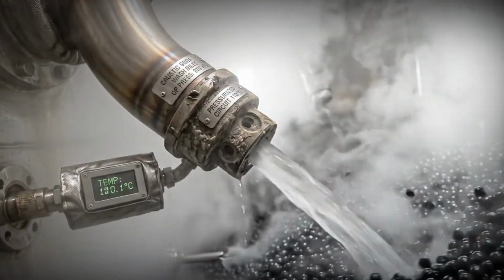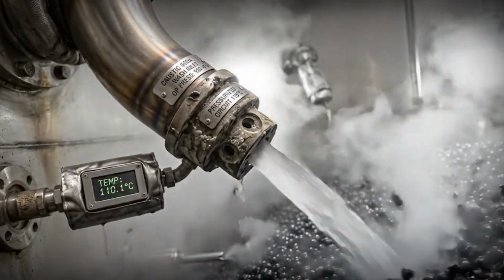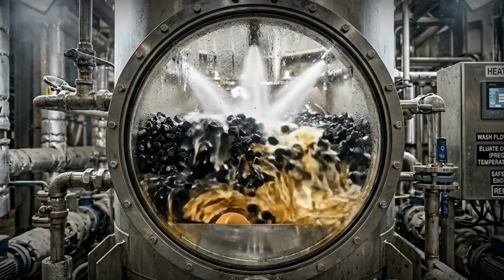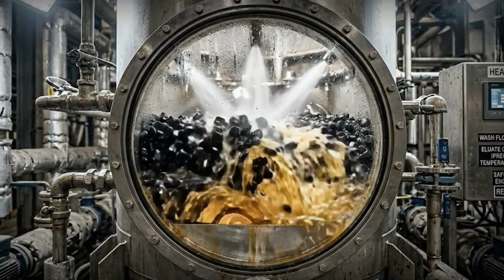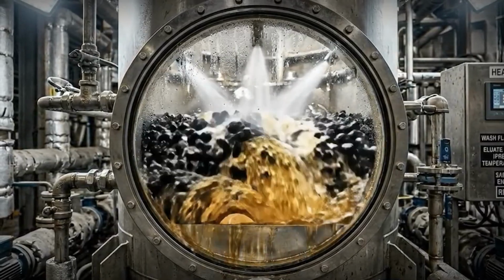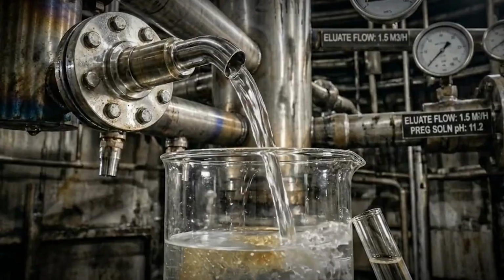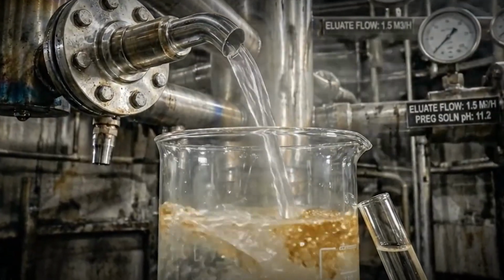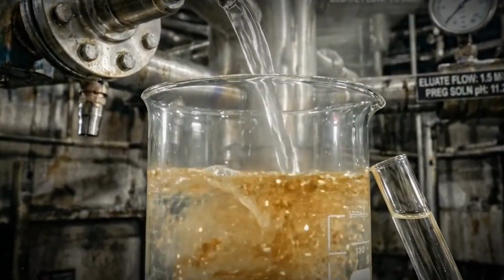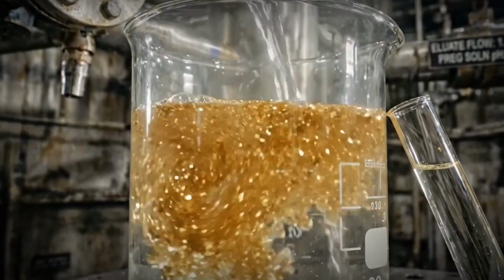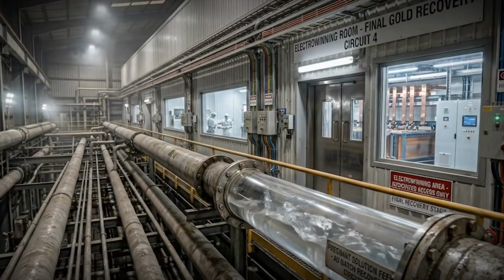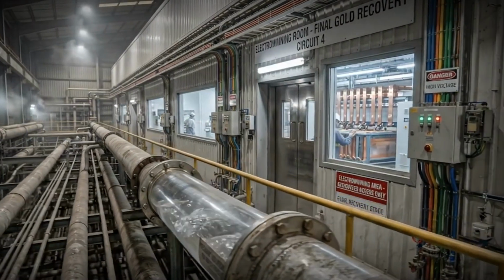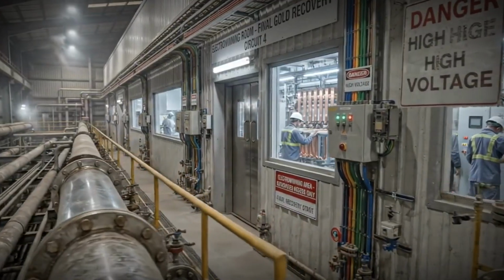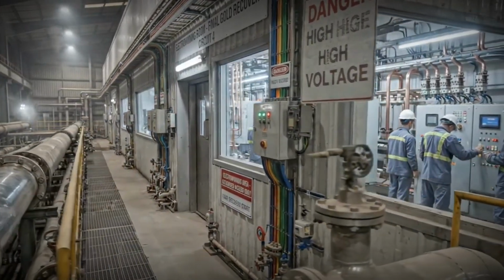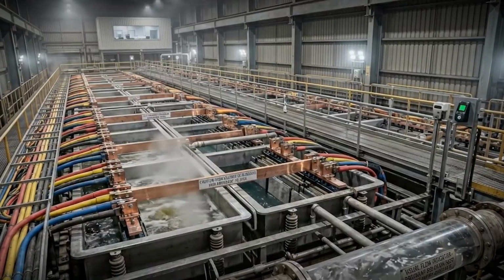This liquid is now called the pregnant solution, carrying dissolved gold in concentrations measured in parts per million. Next, activated carbon granules that look like coarse black sand are added to the tanks. The carbon has an extraordinary affinity for gold cyanide complexes. Within minutes, the dissolved gold adsorbs onto the carbon surface, stripping it from the liquid. The loaded carbon is then separated from the slurry and moved to the elution circuit, where a hot caustic solution strips the gold back off the carbon, concentrating it further into a rich, gold-bearing liquid.